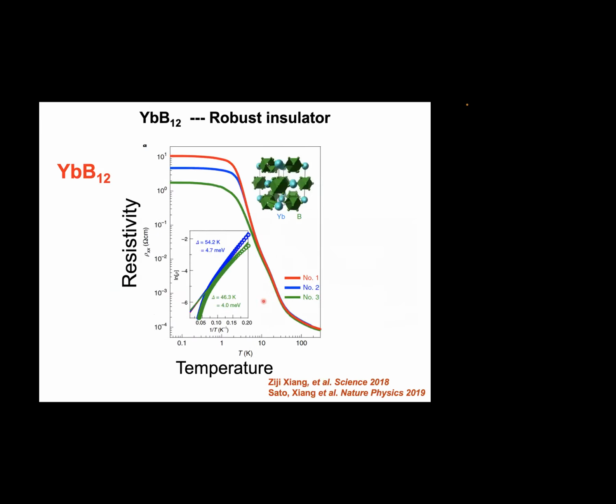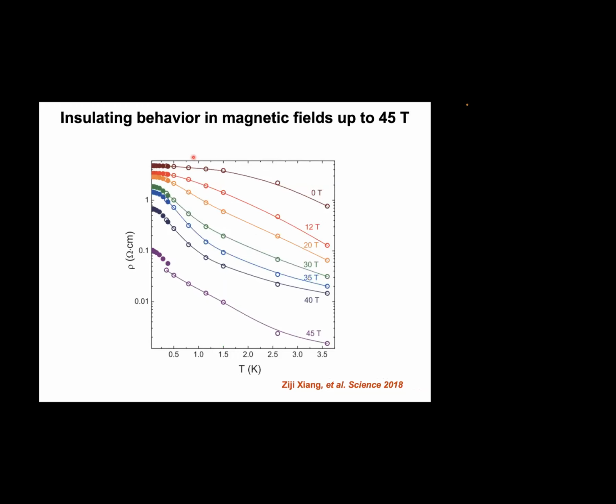And we look at electrical transport, resistivity versus temperature. Again, it just looks like a typical Kondo insulator like SmB6. From room temperature to base temperature, I have almost 5 orders of magnitude divergence of resistivity and the saturation, just like what we saw in SmB6. And even up to 45 Tesla, I still have this semiconductor behavior, like 2 orders of magnitude change, just from 3 Kelvin downwards, right?